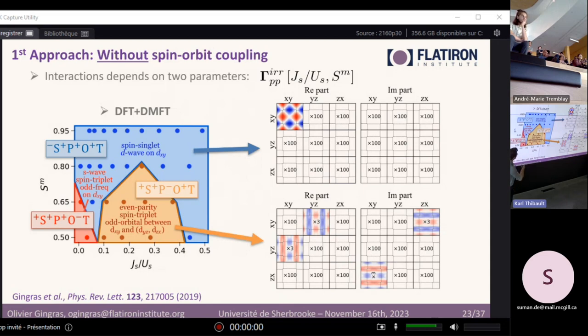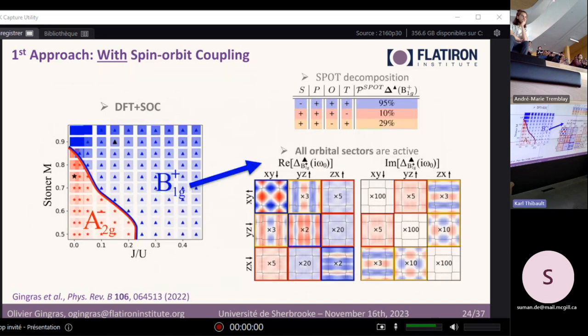But first, I want to see what happens to this orange dome when I include spin orbit coupling. So this is what happened. Basically, it disappears, but actually it doesn't really disappear. What happens is that it mixes with the other states to form just a more complicated state in this case. So we call it B1G because this is kind of a spin orbit generalized D wave, but it transforms exactly like B1G, like the irreducible representation. It's just that now it's much more complex and all the spin orbital components are coupled together because of spin orbit coupling. But you can see that you have this main component that is D wave here.